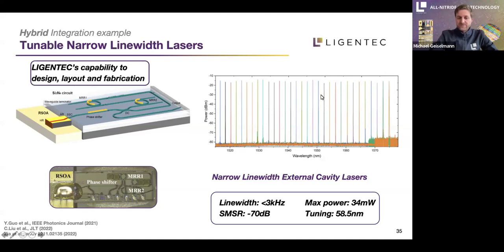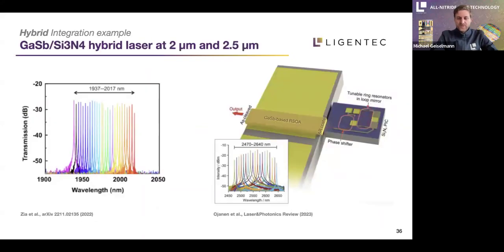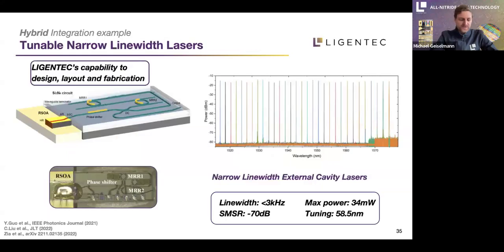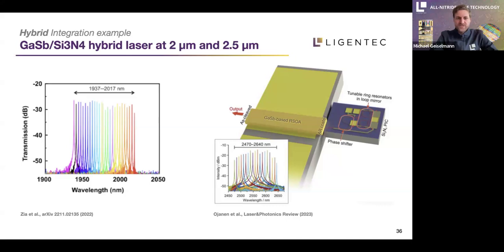Still with a lot of power in the waveguide, in the laser emission, and large tunability due to the heaters that are integrated on top of the silicon nitride waveguide. And the beauty of that is that this was an example for 1550 nanometer, but you can also do the same for other wavelength regions. And here there are two papers that did that on our platform in around 2 micrometer wavelength region and around 2.5 micron wavelength region, where the same concept applies.